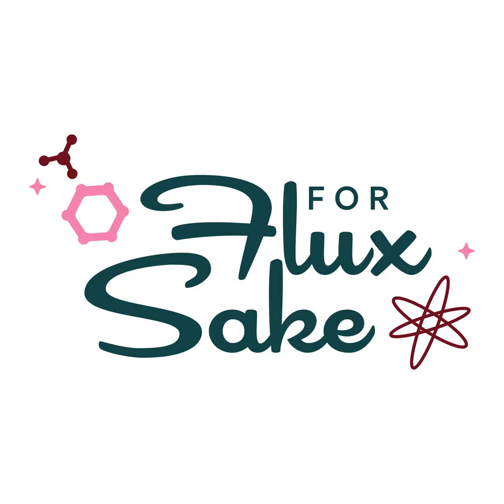When you need to get under cone 10, you need to do something else to the chemistry because those don't work. 90% of the time, in the contemporary context, people use boron. They use materials like Frits, like 3134 or 3124, or they'll use something like Gerstley borate, or we've talked in previous episodes about borate substitutions like Gillespie borate or things like that. So those are all using boron, and boron is a lower temperature glass former that works under cone 10. So that's what those are in there.